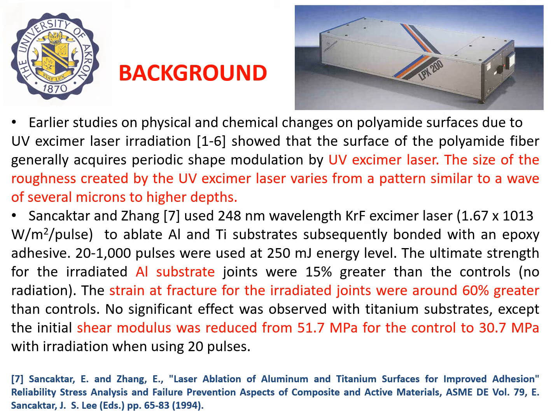Earlier studies on physical and chemical changes on polyamide surfaces due to UV excimer laser irradiation showed that the surface of polyamide fiber generally acquires periodic shape modulation by UV excimer laser. The size of the roughness created by the UV excimer laser varies from a pattern similar to a wave of several microns to higher depths. In the past, we used a 248 nanometer wavelength krypton fluoride excimer laser to ablate aluminum and titanium substrates, which were subsequently bonded with an epoxy adhesive.